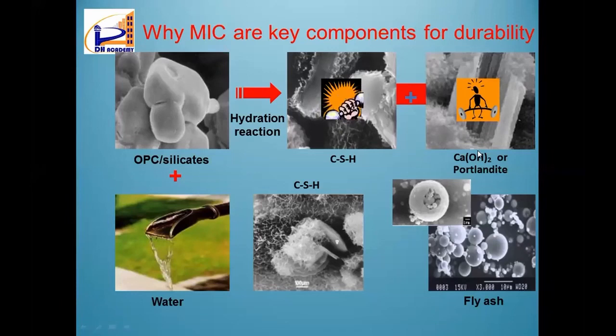If our rebar is bad, it may expand up to 5 times. Just imagine a reinforcement having 8 mm dia. If it is expanding 5 times, it becomes 40. Our concrete, as I said in the beginning, is very strong in taking what? Compressive loads. Because of the expansion of this reinforcement, certain stresses are induced in concrete, and that stress is called hoop stress. Our poor concrete is weak in taking that stress, so it falls. That is the reason why spalling of concrete happened. So what was the villain there? This calcium hydroxide that is leached.